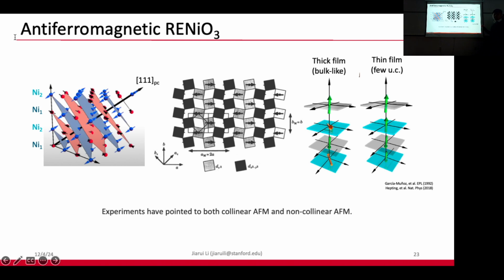Since I mentioned that there are 2 equivalent nickel sites, we can label them nickel 1 and nickel 2. So every other plane, say the nickel 1 plane, they have anti-parallel nickel spins, and so does the second plane and the fourth plane. So the black spins are anti-parallel, but ferromagnetically aligned in plane, and all of the blue spins are also anti-parallel across 2 adjacent planes. And the whole magnetic structure can be modeled by only this 2 spin motif.